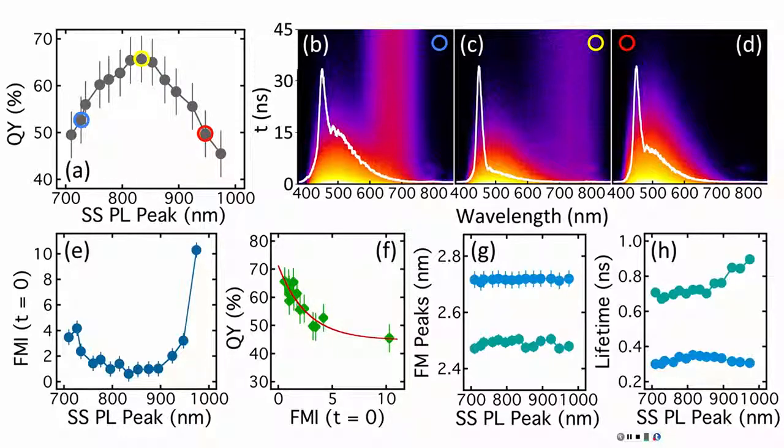And of course, in our case, your K vector depends on the size of the primitive unit cell. If your primitive unit cell is at least 10 times smaller than the size of the system, then your K approach would be fine. But if it's comparable, twice larger, 3 times larger, then of course we cannot really talk about band structure. It behaves more like a cluster, more like a molecule. But for your 4 nanometer or even probably 2 nanometer quantum dots, you're probably safe to use your favorite bulk picture of band structure.